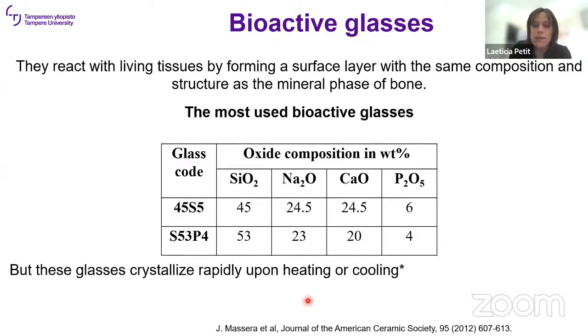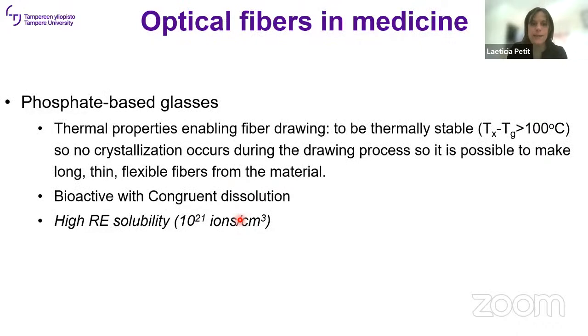You have here on this table the most used bioactive glasses, the 45S5 and the S53P4. They are also commercial glasses, and they are silicate. You have their composition in weight percent here. The problem with these glasses is they crystallize upon cooling or heating. That means that we cannot draw fibers from them. This is the reason that we have worked on the development of new biophotonic glasses.